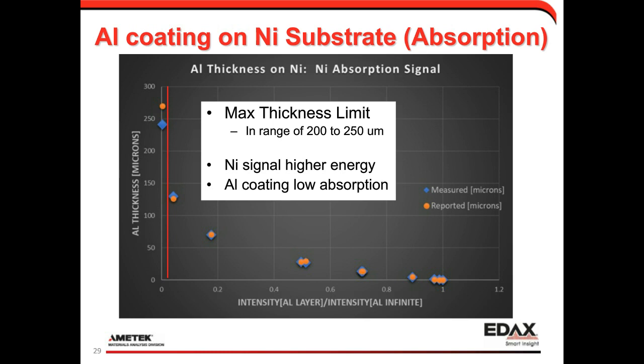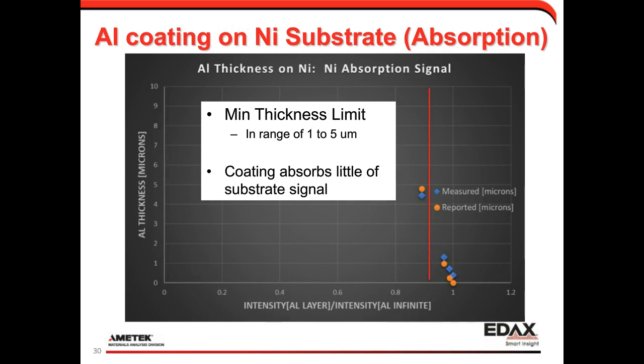As we blow this up to look at where's our minimum thickness limit, what we can see is that we are getting results in the 10% range, around 5 microns or so, and below that we're getting some offsets where the measured values are coming out a lot higher than the actual foil thicknesses. The reason for that is that as the coating decreases in thickness, and it's not very effective at absorbing the nickel signal, we don't have great precision in that range. Looking at the nickel signal, it just looks like bulk nickel. So our minimum thickness limit is in the range of about 1 to 5 microns, somewhere in there.